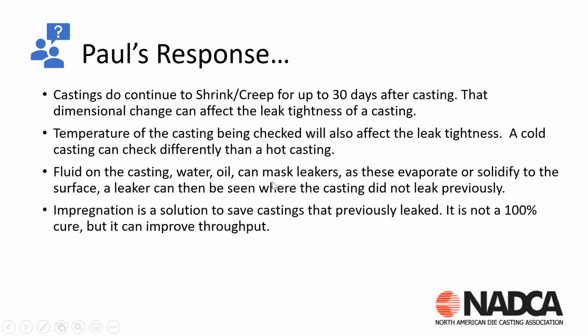More than likely, it's either the temperature or if there's fluid or water or oil on the casting, that can also mask leakers. As those fluids or oils evaporate, they either solidify on the surface or they evaporate and go away. They could create or open up a leak path that was blocked previously. Now, as a side note, anybody doing leak check pretty much knows that impregnation is a way to save castings that previously leaked. It's not a 100% cure, but it can improve the overall throughput of the castings.